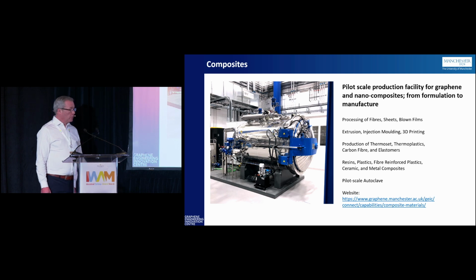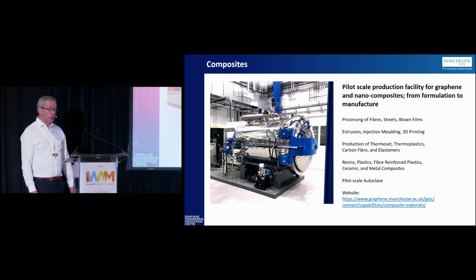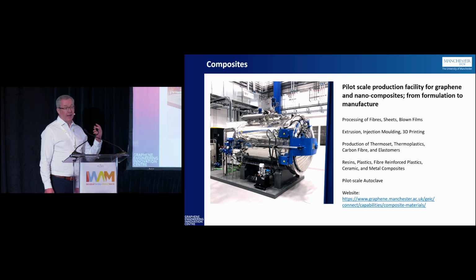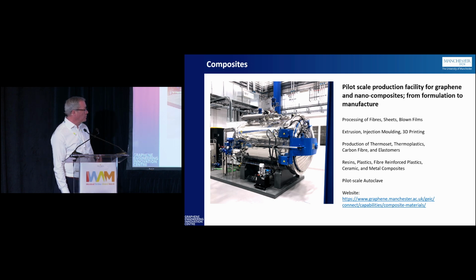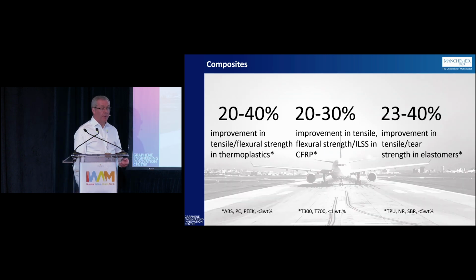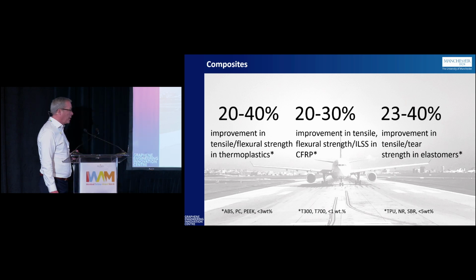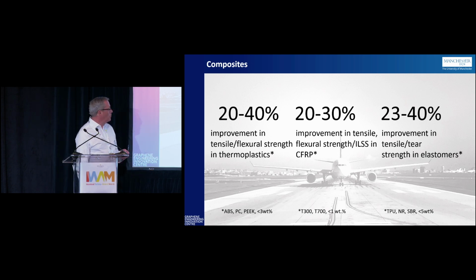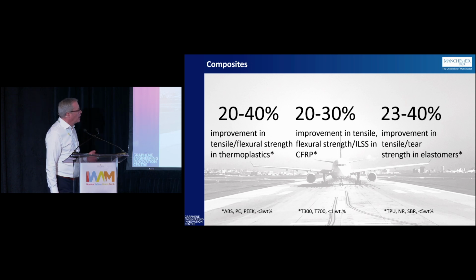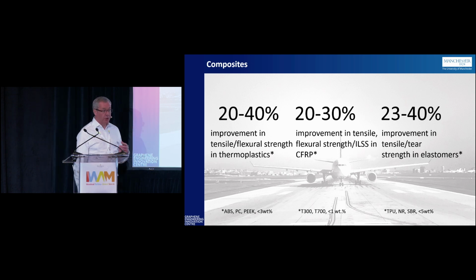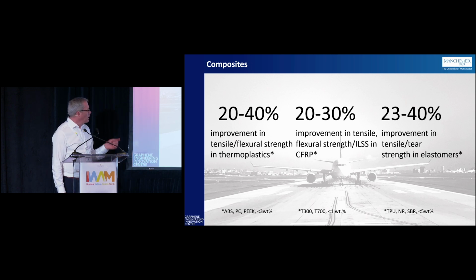So that's construction materials. That was just on cementitious stuff, but we've actually been working in pultrusion systems like carbon fibre reinforced systems, lightweighting of bridges, for example. We've worked with the supply chain to actually deliver humanitarian lightweight bridges, for example, and we've been taking material out in things like pultrusion systems, blown fibre systems, so thermosets and thermoplastics, but very similar. It's how do we start to get graphene and 2D materials into automotive grade plastics or aerospace-based plastics, thermoset CFRPs. It's different technologies, clearly, but we've got a lot of demonstrable data here at the moment, and these are some kind of figures that we're getting quite reproducibly at the Graphene Engineering Innovation Centre in all types of systems.